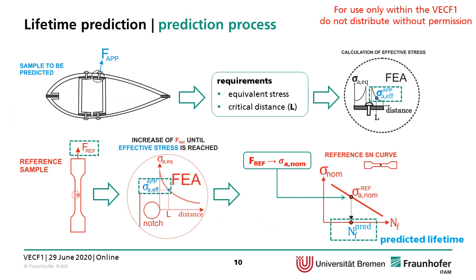Then the process of lifetime prediction was done as follows. So considering the sample to be predicted, which is subjected to a certain force, by having chosen prior the equivalent stress at the critical distance, you have the effective stress. Then, having a reference sample, which has a much easier geometry, in the finite element analysis, you would increase the external force until the same value of effective stress at the critical distance was obtained in the reference sample. Then, taking the reference sample in the SN curve, you'd be able to predict the lifetime of your sample to be predicted.